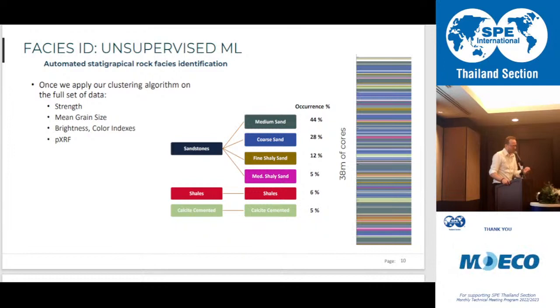This is especially meaningful when you have, for instance, 10 elemental compositions with one grain size log. Those will take advantage of their strength, because they speak more to each other, rather than in front of a single log that represents only grain size. So you need to play a bit with the weight to emphasize some logs compared to others. But I would not say that it's extremely sensitive. If you use an adjustment weight of 3 or 4, that will produce basically the same results. The boundary will change slightly, but overall it remains fairly robust.